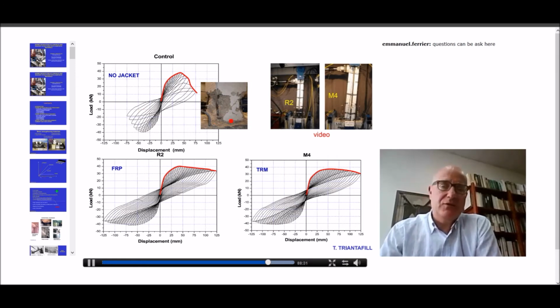That can be used to do local jacketing, to increase the ductility of concrete. As illustrated here, that would be the response of a reinforced concrete column without this local jacketing. You see a typical failure at the bottom. And you see how this column would behave if it is confined by a locally applied FRP jacket. And you get an identical response if this FRP jacket is replaced by a textile-based one. So one can conclude that the effectiveness of those TRM jackets is pretty much identical to that of FRP jackets.